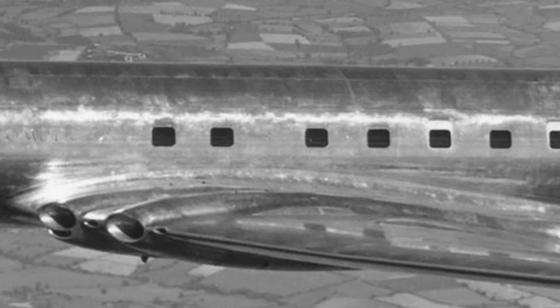After that, they pressurized it to normal flight pressure, cycling it 2,000 times. Later, concerns about metal fatigue arose, so they decided to pressure-cycle the cabin until it failed. It withstood 16,000 more cycles — a total of 18,000 cycles before failure — well above the planned 10,000-cycle life of the Comet. There was no doubt that the Comet was safe as far as pressurization was concerned. This is why metal fatigue of the fuselage was ruled out in the original investigation of the Elba crash.